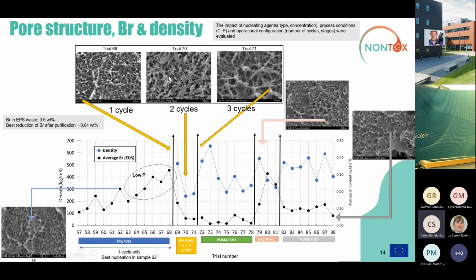it was possible to come to these nanocellular structures where the content of bromine was taken from 5,000 ppm down to levels close to 400, where it was really not possible to remove further. We believe it was because of the presence of these polymeric brominated flame retardants that were really not possible to remove. But then it was proven that it's possible to perform the two operations in one single reactor.